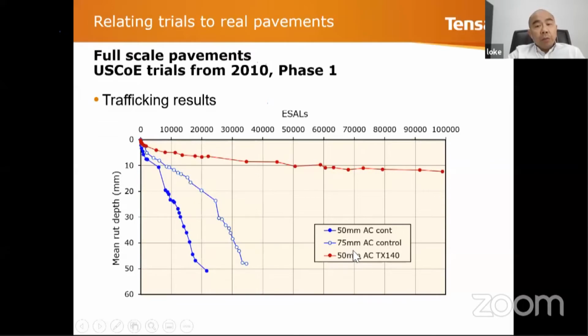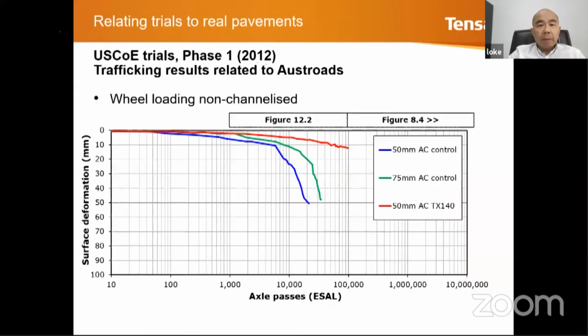And what you can do is, if you add a layer of geogrid with 50 millimeters of asphalt, you can see that it can go on until 100,000 passes with rutting of less than 12 millimeters. And that is a very interesting and well-performed trafficking result. Okay. So you can replot these in the Austroads chart.